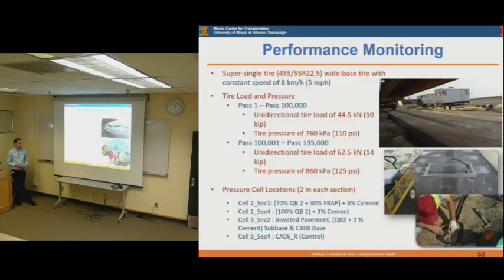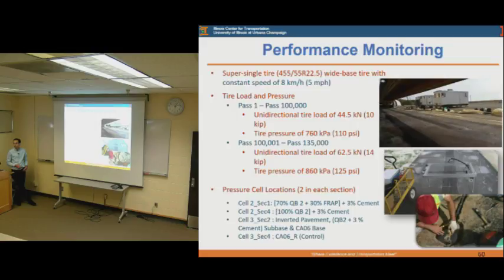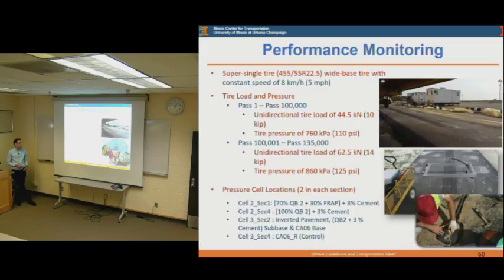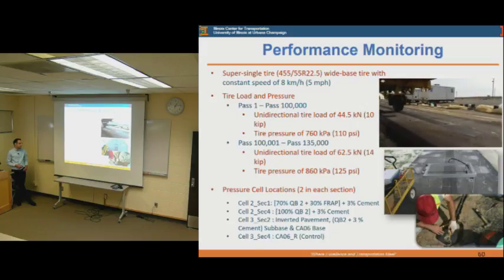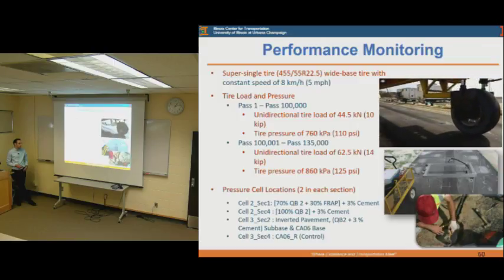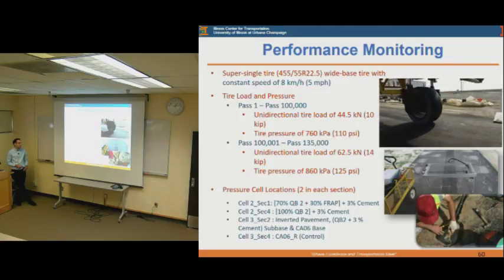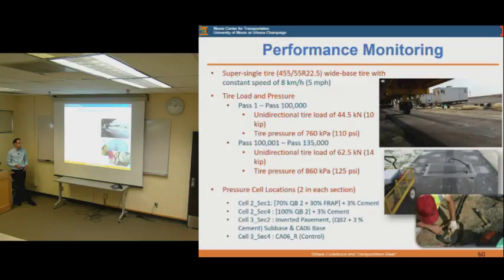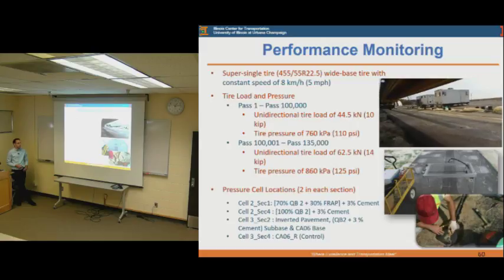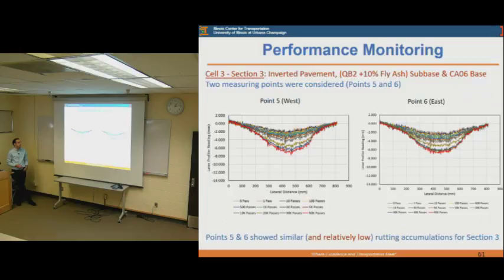Also, in some of the test sections, or in 4 of them to be exact, we instrumented the test sections on top of the subgrade with soil pressure cells, which Professor Al-Qadi kindly helped us with the field installation of, with his expertise. The test sections that were instrumented were the first and last test sections of cell 2, which are the one that has the quarry byproduct with the FRAP and the cement, and the quarry byproduct only with the cement. And then in cell 3, one of the inverted pavement test sections, which is the one that had the quarry byproduct with cement as a subbase, and the control section at the end. We were also monitoring and collecting data from the pressure cells and from thermocouples for temperature along the experiment.